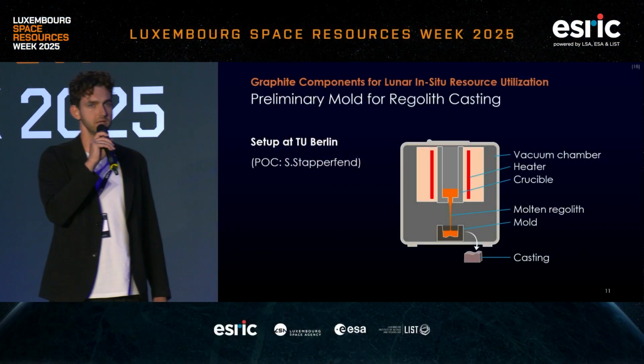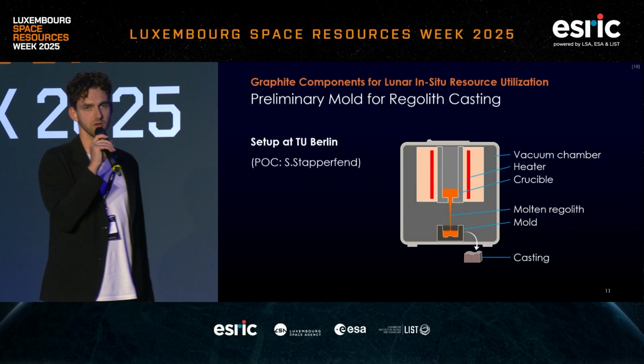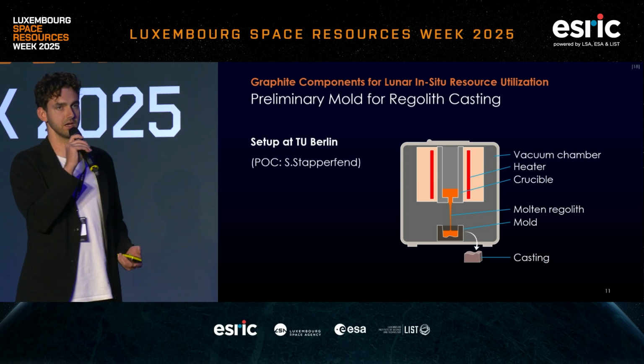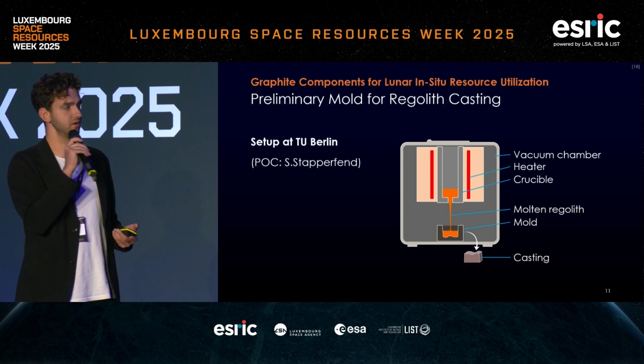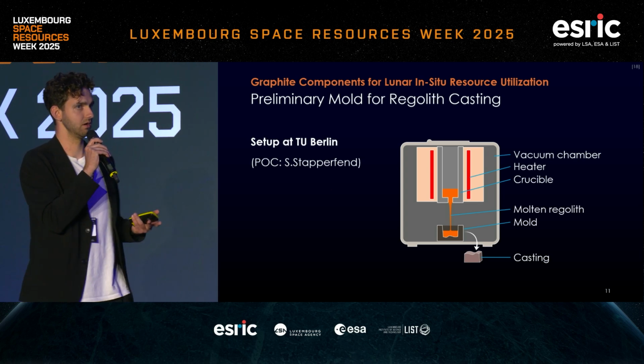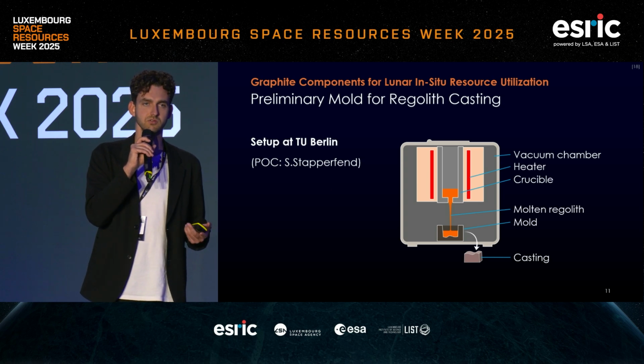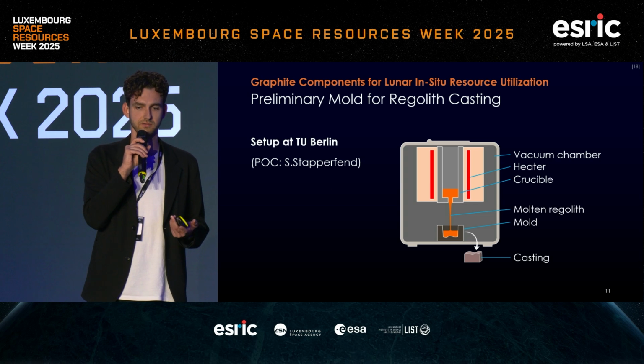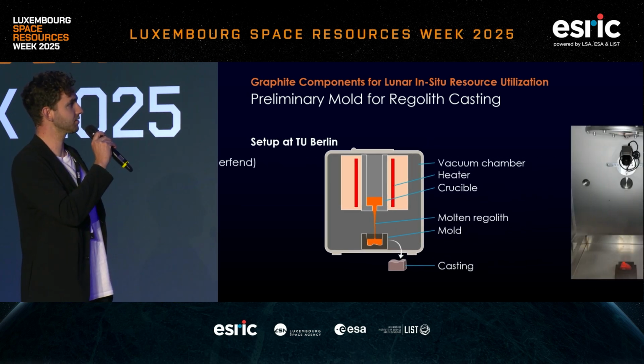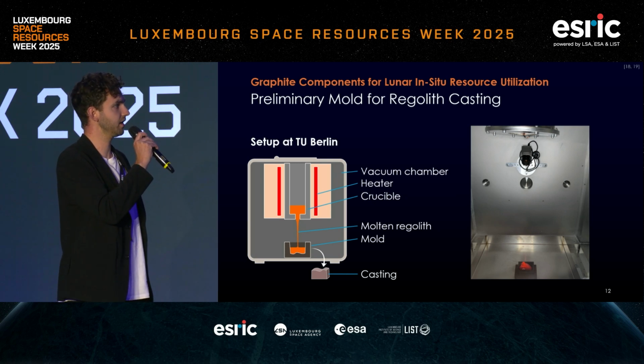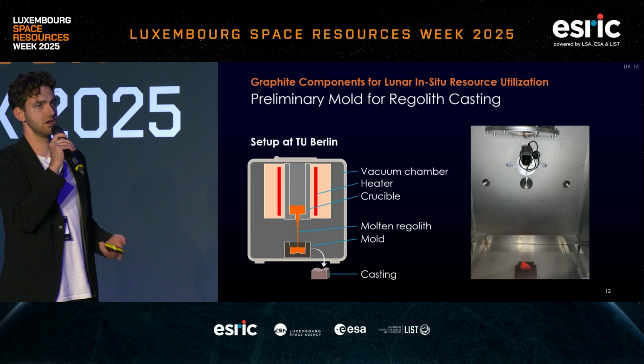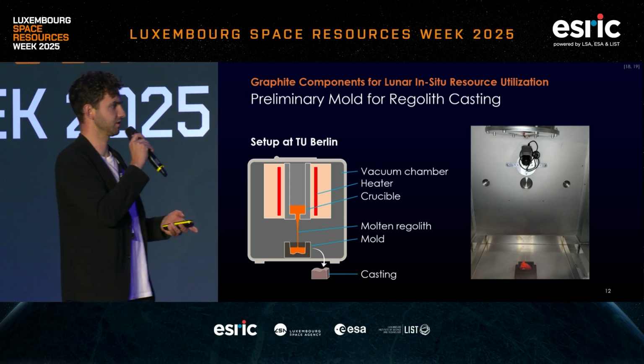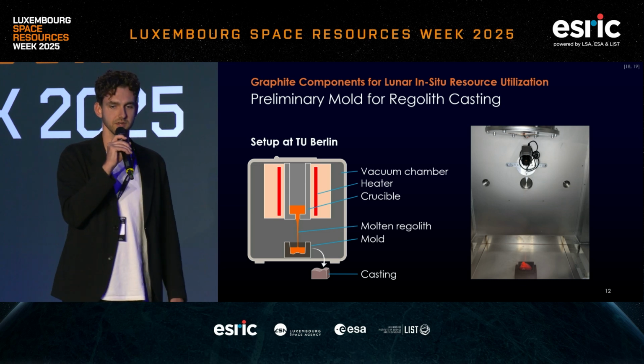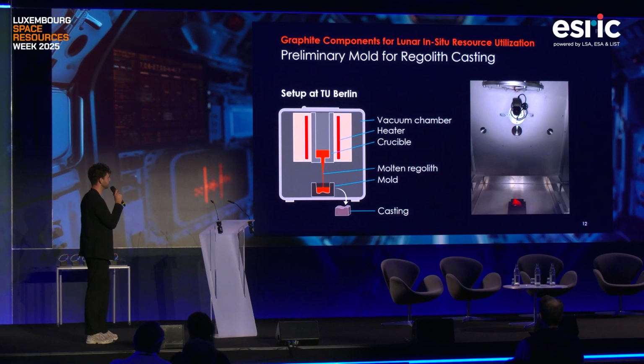Next up, I'm sure many of you are familiar with Simon's work at TU Berlin. He has a vacuum chamber with a crucible surrounded by an electric heater to melt regolith and then extrude it through a nozzle and into usually a powder bed. But the idea was to replace this powder bed with a mold to do casting of glass samples. And we have created a little graphite mold for that. Because we are working in vacuum here, we don't have to care about the temperature, actually, because graphite in vacuum is thermally stable up to 3000 degrees centigrade. And on the right-hand side, you can see the experimental setup. On the top, the vacuum chamber, and in the bottom, the graphite mold with the freshly molten regolith.